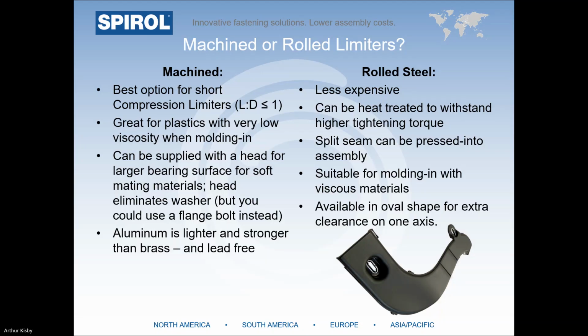However, for short compression limiters, particularly when the length to diameter ratio is less than 1, it makes most sense to use a machine limiter because it is difficult to roll a limiter that's short and keep the ends square. Also, machine limiters are preferred in mold-in situations where the plastics have very low viscosity, since there are no seams for the plastic to seep into. Machine limiters can be supplied with a head for a larger bearing surface for soft mating materials. A head also eliminates a washer. In most cases, though, we suggest just using a flange bolt instead.